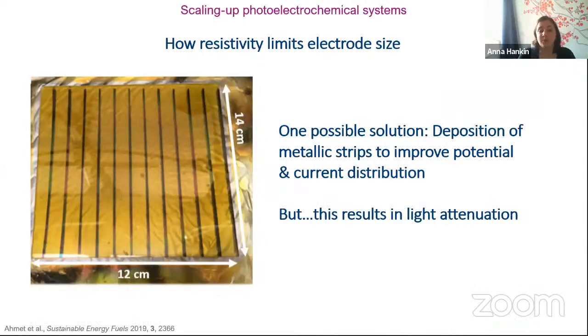There've been some approaches to mitigate these effects. So on top of the FTO, you first put some sort of metallic grid that helps collect and distribute all the electrons to the semiconducting layer. And it's been shown that this really increases the performance of the photoelectrode. But of course, the more you add these conductive strips or whatever, the more light you attenuate. So there's basically a fine balance between this offset in resistivity and optical transparency.